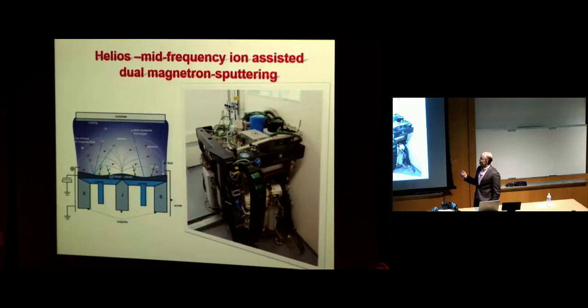The machine is called middle frequency ion assisted dual magnetron sputtering, and I will try to explain what each word means. Basically, when we deposit one material, instead of one target, we have two targets, and it's shown here, we have targets of the same material. This is why it's called dual. We apply a positive charge to one target and a negative charge to another target, and we change this with middle frequencies. In our chamber, due to a plasma source, we have a plasma, and depending on what kind of charge our target has, negative or positive, the electrons or ions fly in the direction of the target with large speed. In such a way, we evaporate or sputter our material in the direction of the substrates.